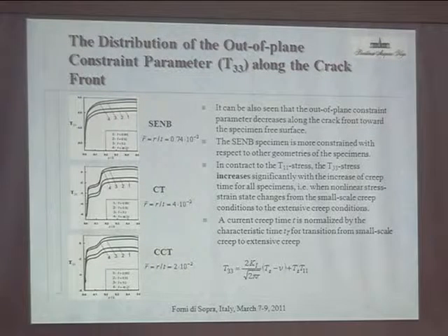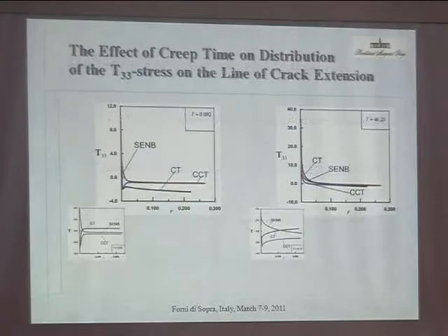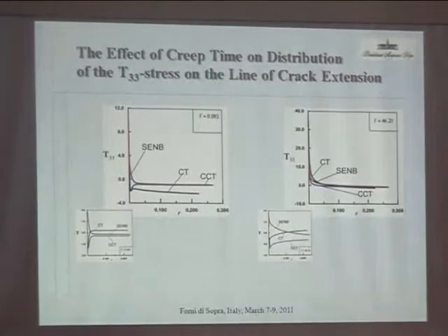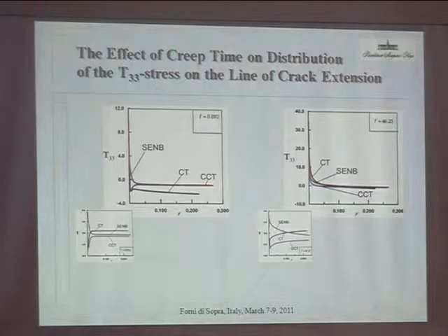From these pictures, it can also be seen that our out-of-plane constraint parameter decreases along the crack front towards the specimen free surface, this region. And again, the single edge specimen is more constrained with respect to other configurations of specimen. And I would like to notice that in contrast to T11 stress, the T33 stress increases significantly with increase of creep time for all specimens.